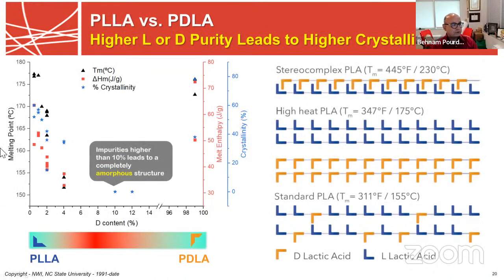So the graph on the left just shows you the D content. On the 0, it's a pure PLLA, 100% is pure PDLA. And what's interesting, when you start adding a little bit of D, you notice that the melting point drops very significantly. And so this is actually an opportunity because when we use a sheath-core structure in nonwovens, we could essentially do that and create a lower melting sheath that would facilitate bonding a lot better than we do today. And of course, if you look at the crystallinity, it impacts all of the various properties. At some condition, you might get a stereocomplex. If you take the PLLA and PDLA, especially at about a 50-50 ratio, you would form a stereocomplex. And this becomes a very high melting point, high heat resistant PLA.